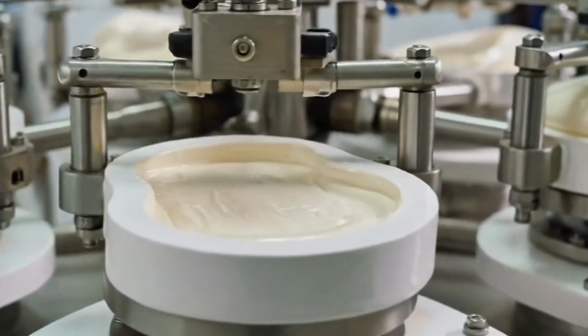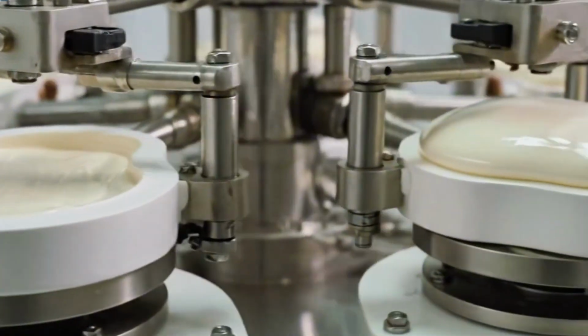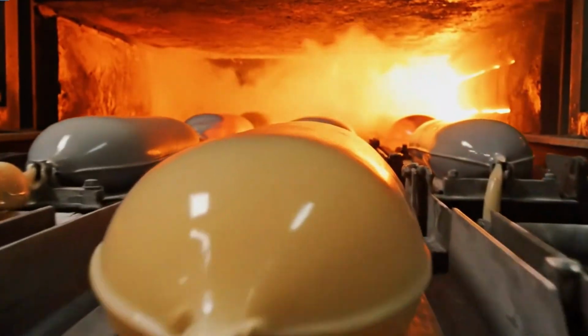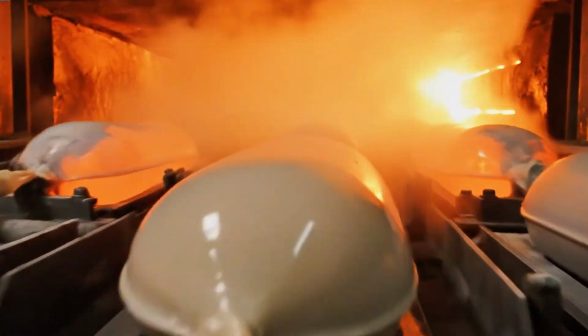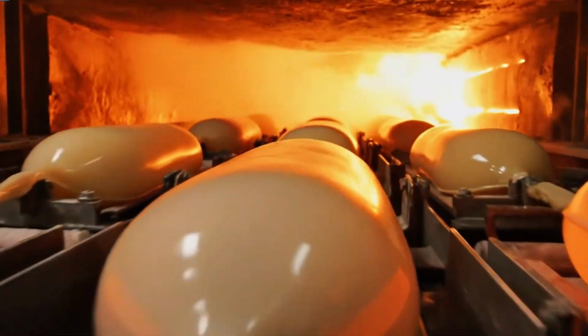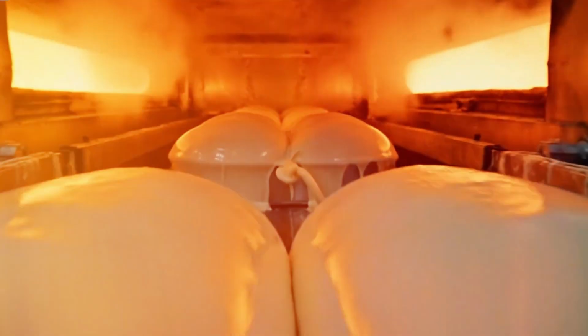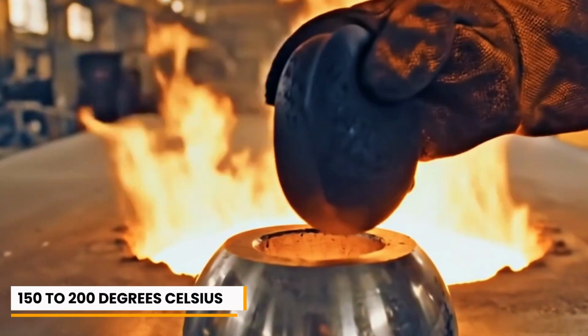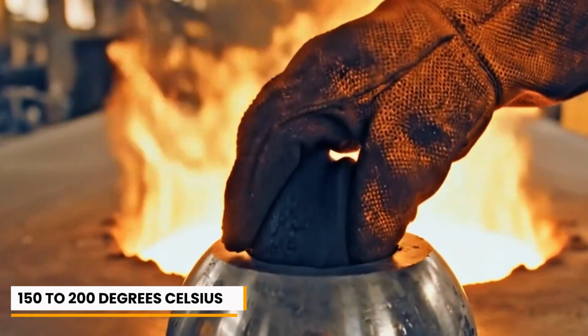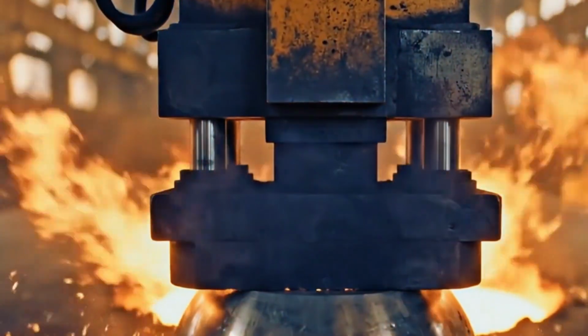During this process, sulfur creates chemical bridges between rubber polymer chains, converting the soft, sticky material into a resilient, elastic solid. The temperature and duration of vulcanization are precisely controlled, typically ranging from 150 to 200 degrees Celsius for several minutes, to achieve optimal properties.